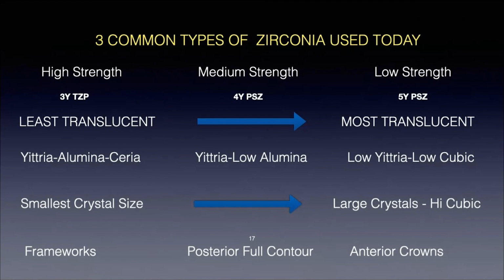And we haven't had one break except on a canine with a natural premolar. When it went into working, the premolar moved a little and the canine cracked. That's the only one we've been able to detect. So we don't use those on a canine. But they still use a 3Y zirconia, and it's very opaque.